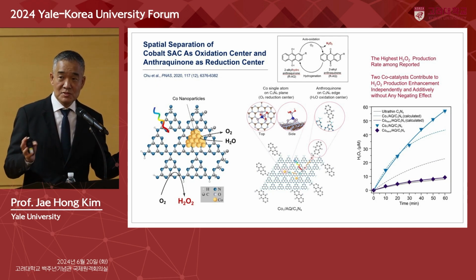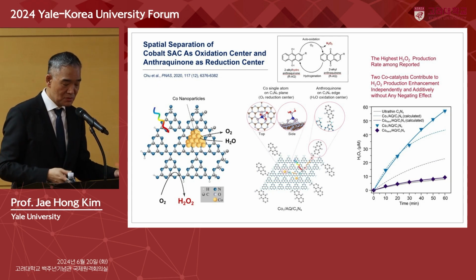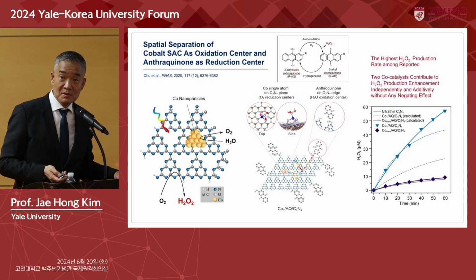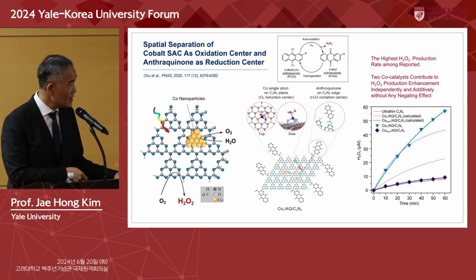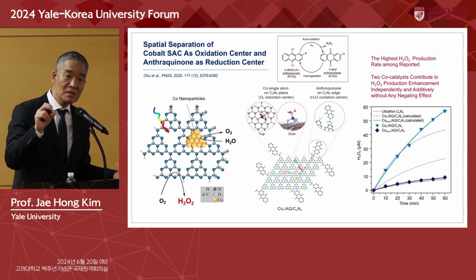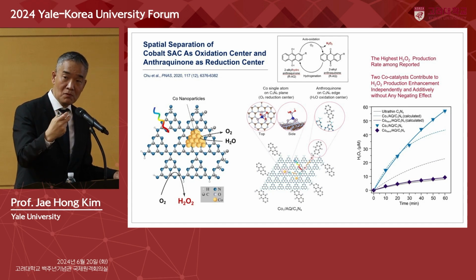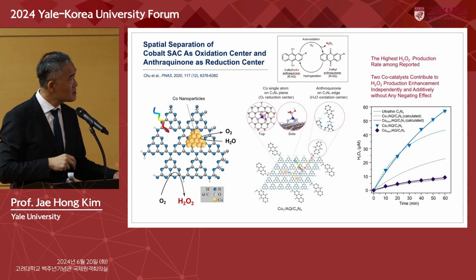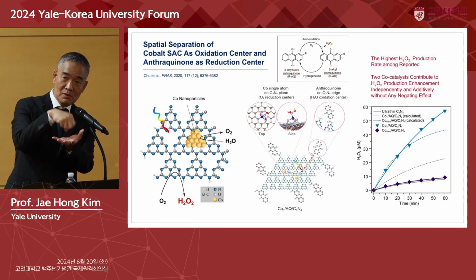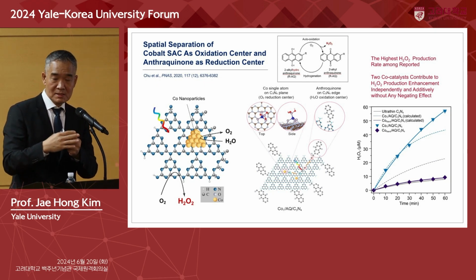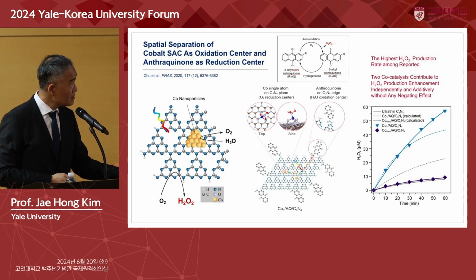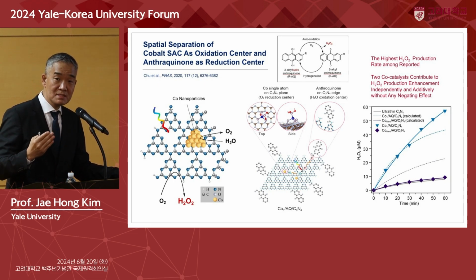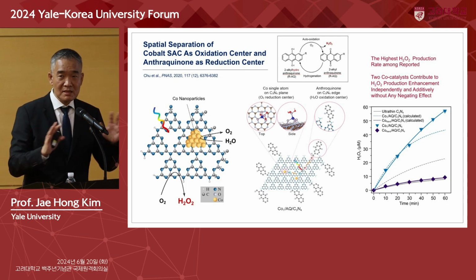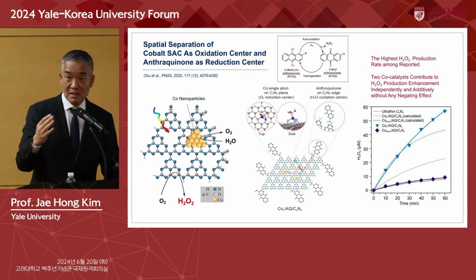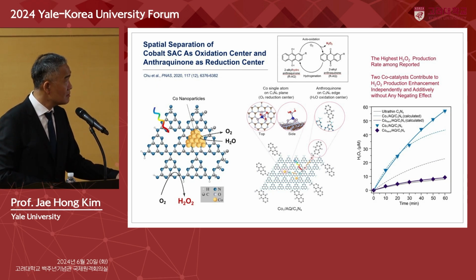There is quite a lot of research on how to separate the reduction co-catalyst and the oxidation co-catalyst. We just happened to have a carbon nitride substrate. So what we did was add anthraquinone on the side of the carbon nitride, and add cobalt single atoms in the holes of the heptazine ring structure of the carbon nitride. Basically, you just load cobalt single atoms one by one. Because of that structure, cobalt and anthraquinone have to be separated. The major finding was that the hydrogen peroxide synthesis from the oxidation catalyst and reduction catalyst was additive, not canceling each other. I think this discussion may be too much detail, but I'll be happy to explain more if anyone has more questions down the road.